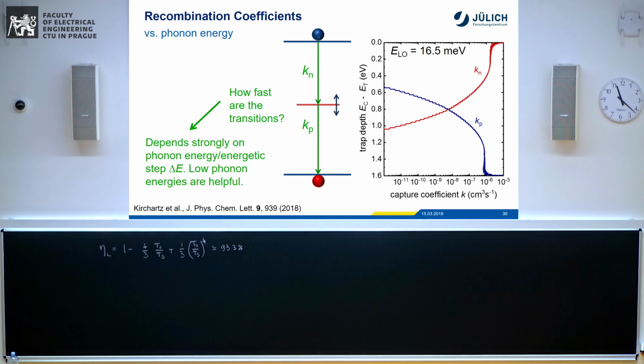And in this paper, we just put in the values, the material parameters we know from these lead-halide perovskites. And this is a graph that's slightly different than the one I've shown last year, hopefully a bit more illustrative. And that tries to just explain how high these transition coefficients, recombination coefficients are as a function of the position of this defect level.